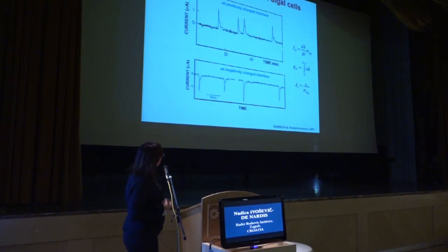The information that we can get from those signals is that we can integrate the area beneath the signal and calculate how much surface charge becomes displaced by the cell, and this charge is proportional to the cell size. And further, by taking the ratio of that displaced charge to the surface charge density of the electrode, we can calculate the contact area that the cell forms at the interface.